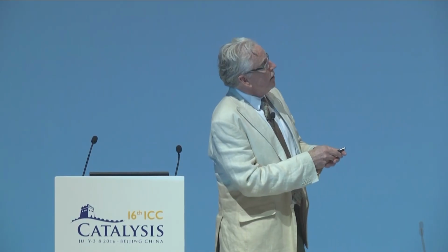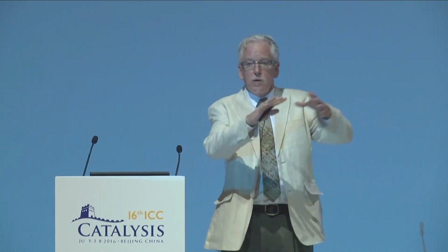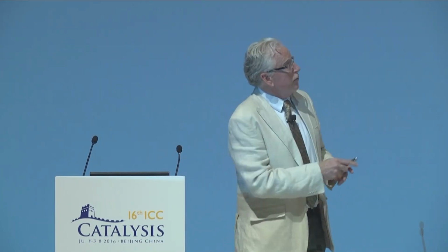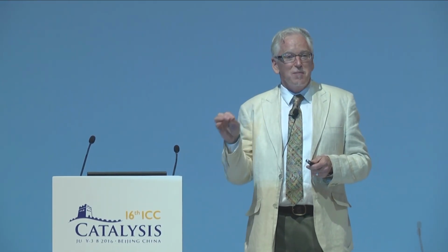Consistent with this trend, gold monomers bind slightly more weakly than copper to ceria. If you look here, gold's here, copper's there. Gold binds more weakly than copper. In fact, for monomers, this is basically the large particle limit for the adhesion energy. But for monomers too, you see a similar qualitative trend. Those 2 points are, as far as I know, the best experimental benchmarks of adsorption energies, the only experimental benchmarks of adsorption energies of metals on oxides of the type that are interesting in catalysis, and so they should be used to see whether density functional theory is doing well at those kinds of approximations.